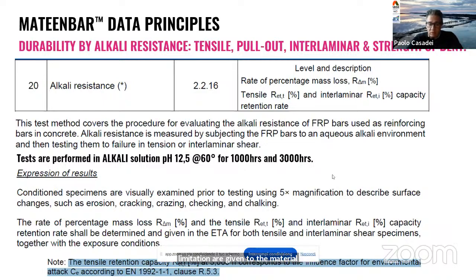Clearly, this is a very important test to perform. So when looking at the material, this is something that we need to look at first, more than the mechanical properties themselves, because clearly we may have a very performing material, but for many reasons, pultrusion may not excel. And in that case, voids and capillarity may provide problems to the product. And so similar to what happens with any construction material, this is something very important of which we need to be aware.